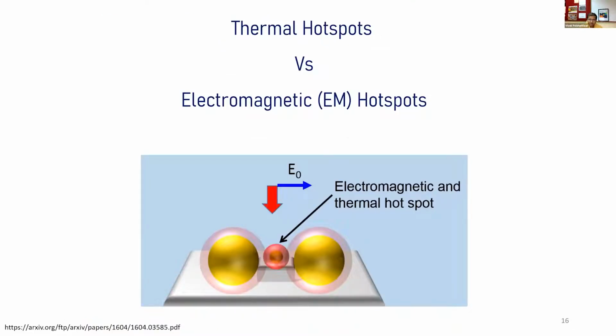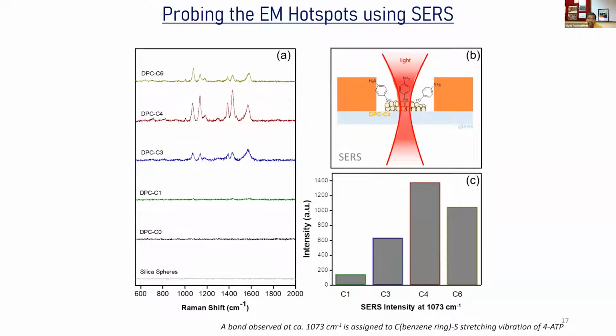We also wanted to see the thermal hotspot, and the electromagnetic hotspot. So for that, we did SERS, and we observed that C4 has the highest enhancement of the signal. The excitation assigned to 1073 centimeter inverse, and you see C4 has the highest intensity signal. That means it is enhancing the SERS signal the best, and that indicates that it has a larger number of electromagnetic hotspots as compared to C3, C6, and C1.